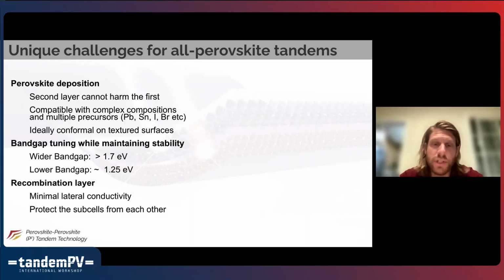Or you can develop a deposition method where you don't actually cause any problems to the first cell by depositing the second. For example, a vapor deposited material that doesn't harm the first cell. Ideally, it's compatible with complex compositions because we need to make both wider band gaps and lower band gaps than most people make when they're making perovskite solar cells. Which means we need to include other elements like tin and bromine. And ideally, it's conformal on textured surfaces because, as we've heard in many of the talks, texturing your cell, whether it's a silicon cell or a perovskite cell, has some serious advantages in terms of light management.